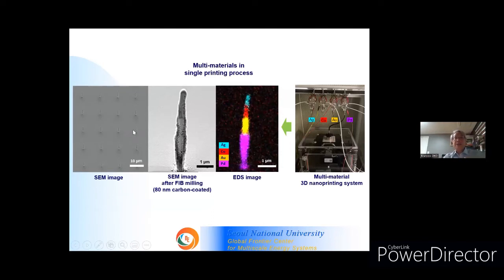While making this high aspect ratio wire, you can change material using 4 different spark discharge sources. The advantage of the wire-to-cylinder type spark discharge is that you can replace your wire and cylinder easily. So if you change silver, copper, gold, palladium, you can change material. Initially you deposit palladium first, then gold, copper, silver, so multi-material can be deposited on a single three-dimensional structure, or you can also deposit alloy or any other type. You just change the source.